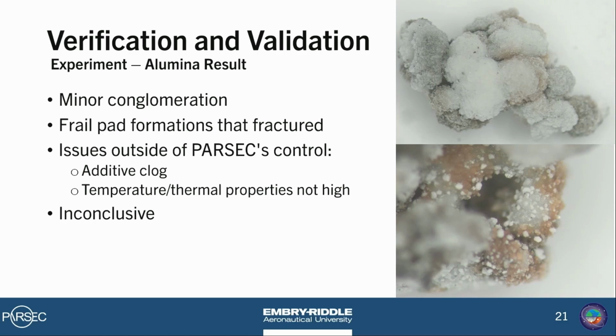Issues that we had with this test include inconsistent flow rate thanks to the alumina clogging our thermal sprayer feeding system, and thus we have deemed the alumina tests as inconclusive because they showed some promise, although it is primarily an issue with our deployer or our testing apparatus that led to the inconclusive results.